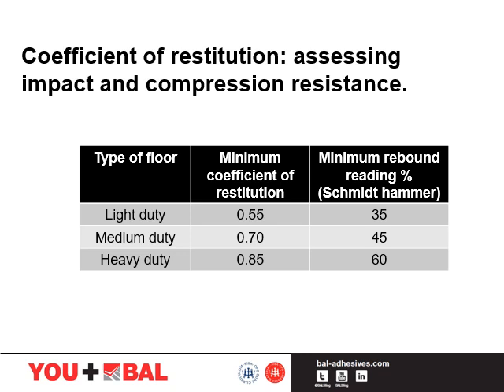The coefficient of restitution can be determined by dropping a 19mm, 28 gram steel ball from a height of 1 metre and recording the rebound height of the ball. The table here shows figures for both coefficient of restitution as determined by the dropping ball test and by the use of a Schmidt hammer for comparative purposes.